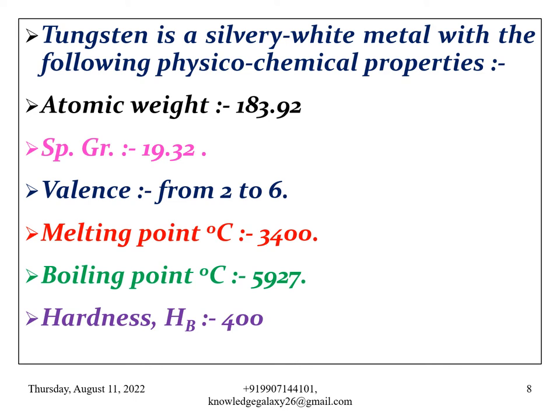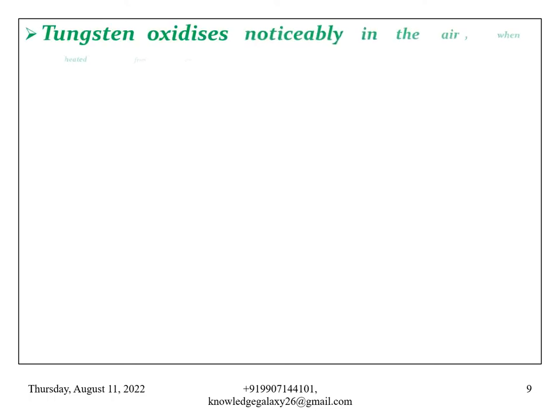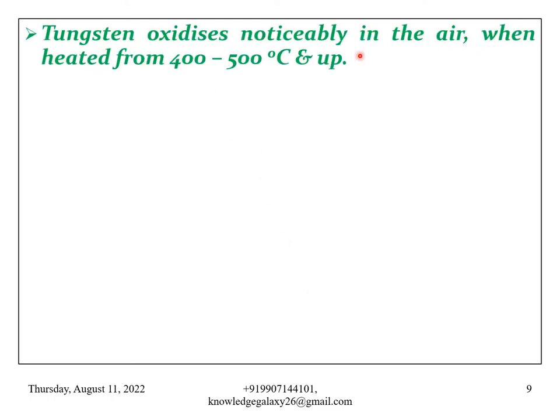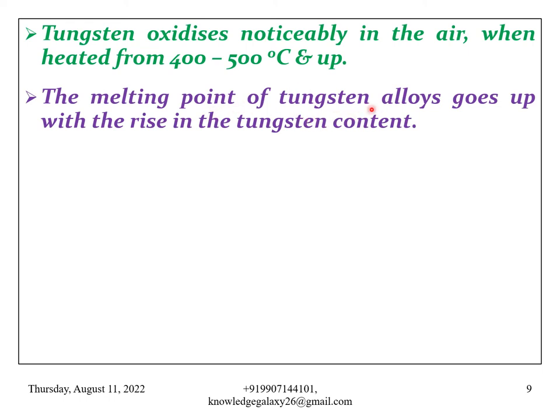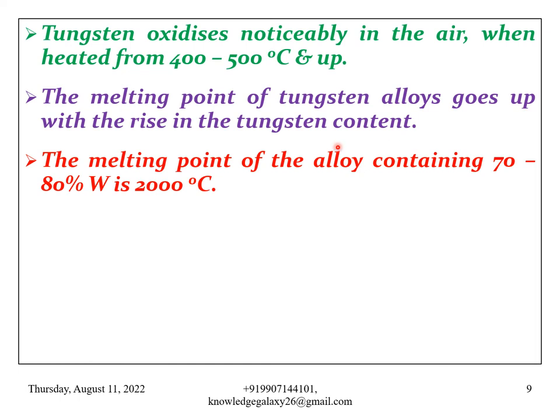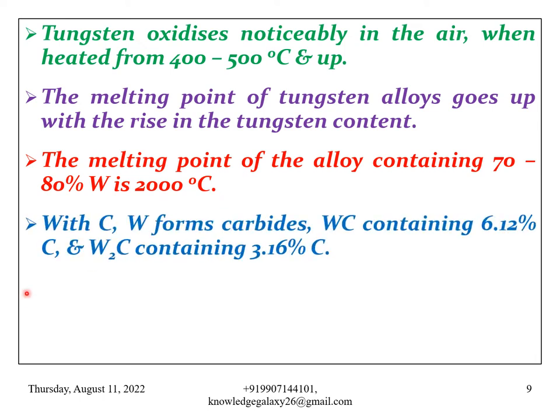Hardness: it has a hardness of HB 400. Tungsten oxidizes noticeably in the air when heated from 400 to 500 degrees Celsius and up. The melting point of tungsten alloys goes up with the rise in the tungsten content. My dear friends, this is a very important aspect. You do remember always that the melting point of tungsten alloys goes up with the rise in the tungsten content. The melting point of an alloy containing 70 to 80% tungsten is 2000 degrees Celsius. And with carbon, tungsten forms carbides, that is tungsten carbide containing 6.12% carbon, and tungsten dicarbide, that is W2C, containing 3.16% carbon.